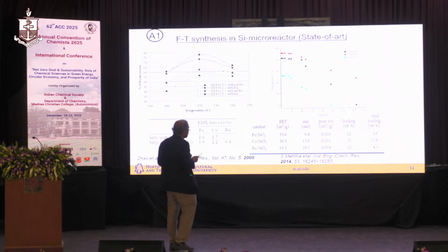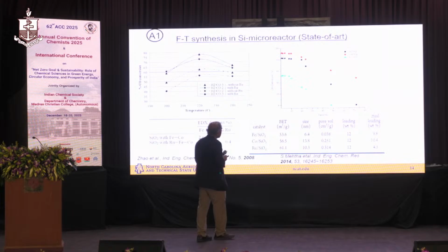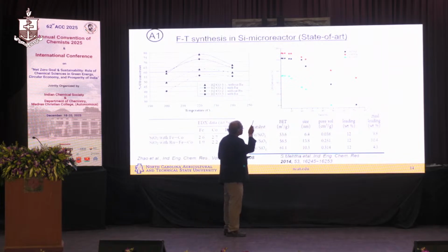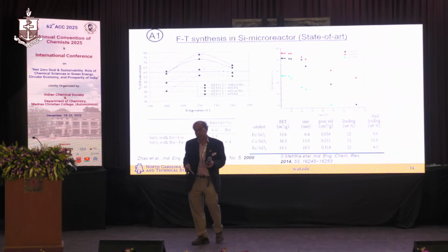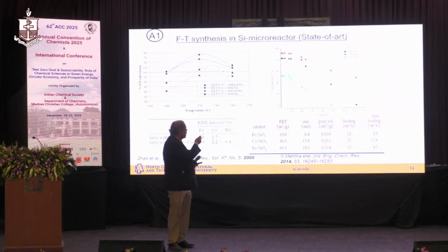And what we found, which is consistent with what is reported in the literature, is that iron and cobalt, which are the workhorses in industry, are very stable, and the ruthenium deactivates much faster. And as you know, ruthenium is very expensive. Okay, so this is what we did in Louisiana.